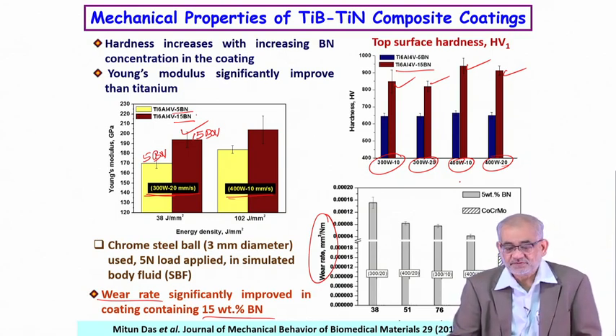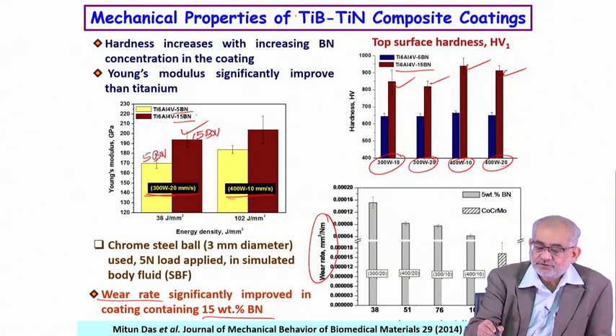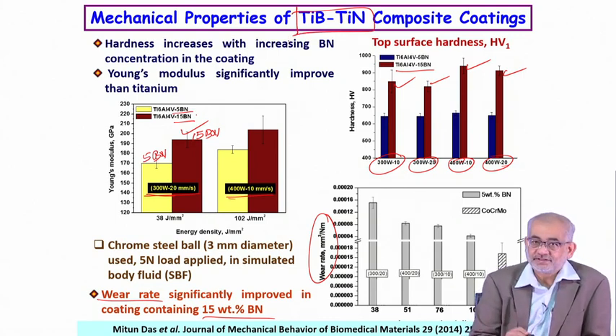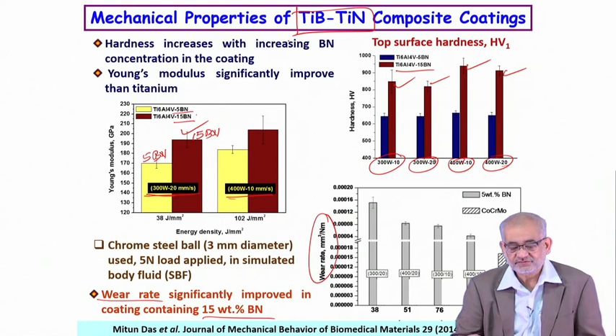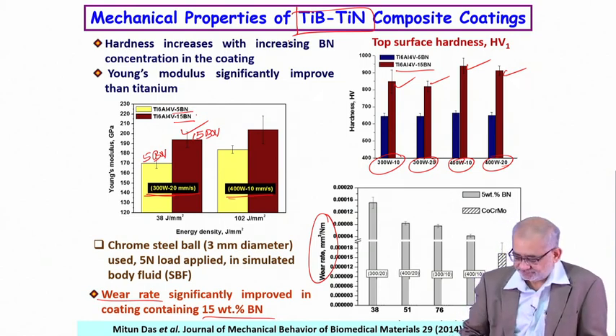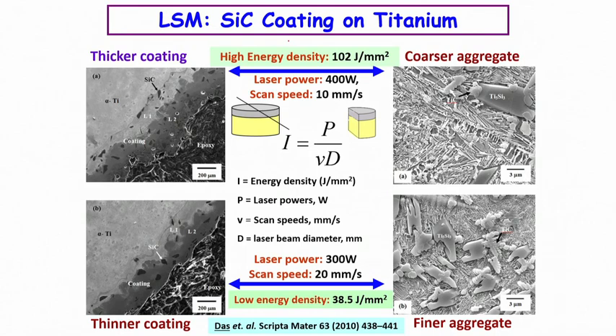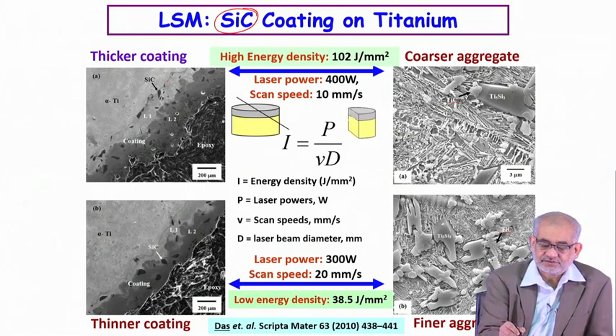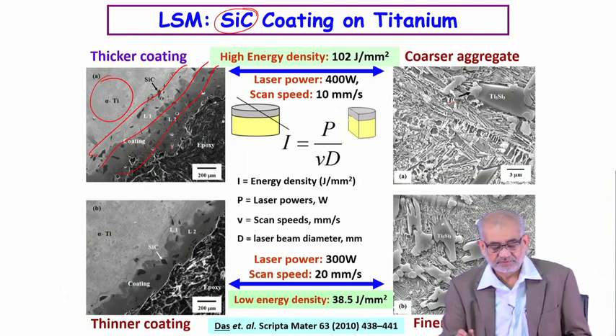So leaving aside those experimental details, what is important is that we are able to produce such an exotic combination of a boride and a nitride using such composite coating, and in this particular case, laser is the agency with which we are able to create such composite coating. We can also create similar coating of silicon carbide on titanium using similar laser-based techniques, and so this is where you see that. So this is the substrate, and this is the coating layer that we have developed, and so you can have multiple coating layers, and this is of course the molding material.